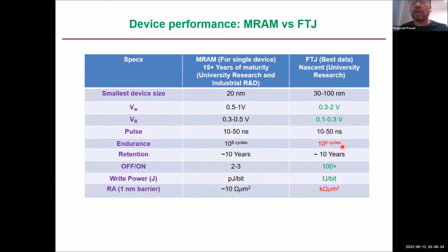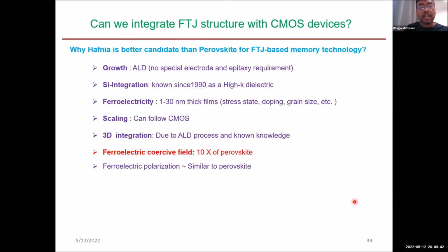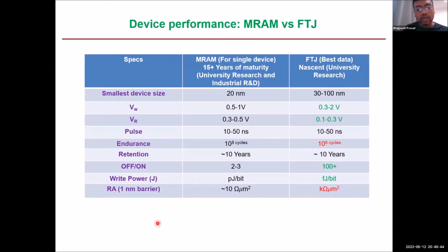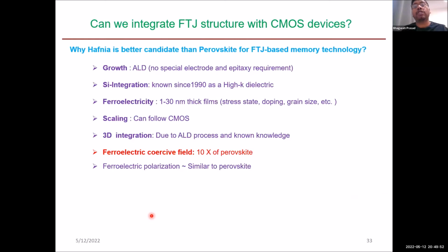The two things one needs to work on are how to improve the endurance and how to reduce the RA, which means you have to make thin barriers. Okay, so this is what we tried. How can you achieve it? Basically you need a thin barrier, which means you need to stabilize ferroelectricity all the way down to 1 nanometer, even smaller than 1 nanometer, and this is more possible with the new hafnia based systems. It seems that hafnia based systems are better than perovskite systems in terms of compatibility with CMOS, and from almost all aspects, like growth and silicon integration, you can achieve ferroelectricity all the way down to 1 nanometer.